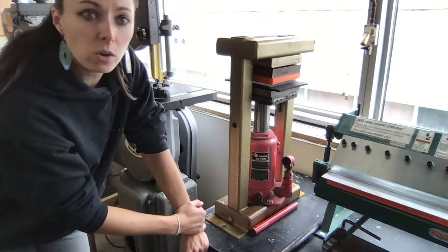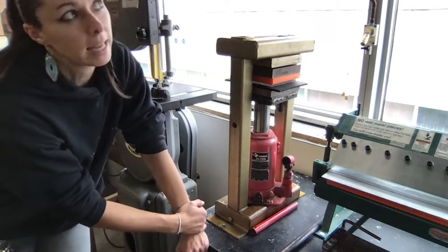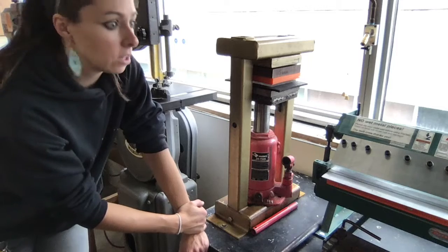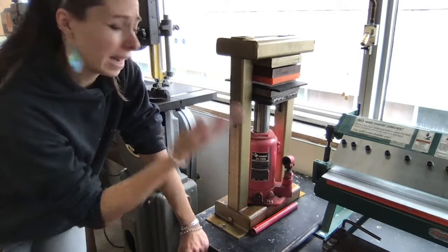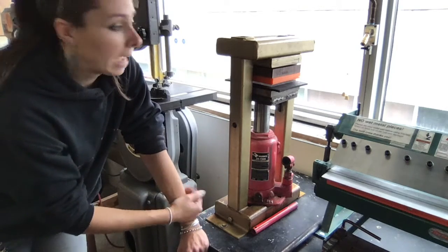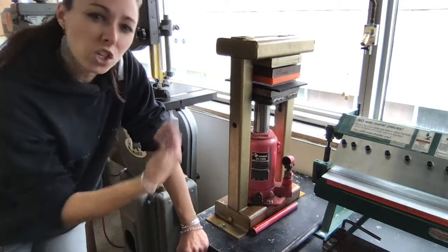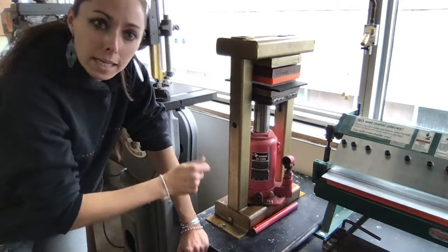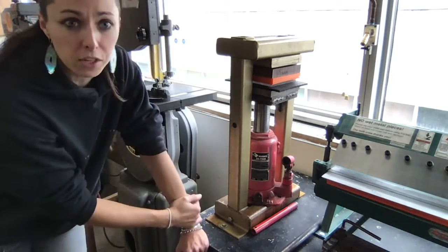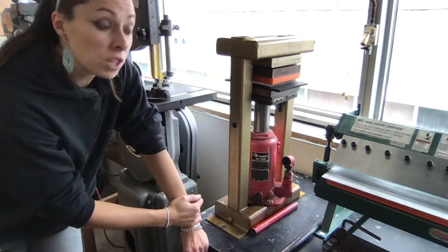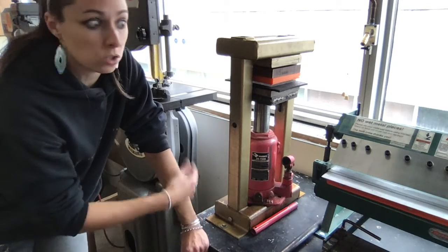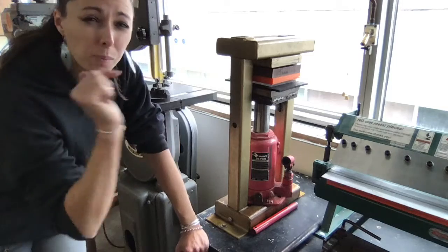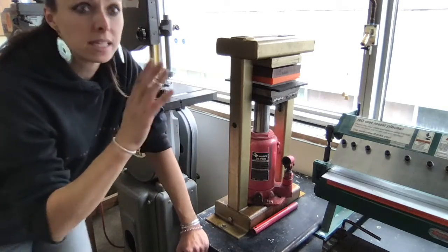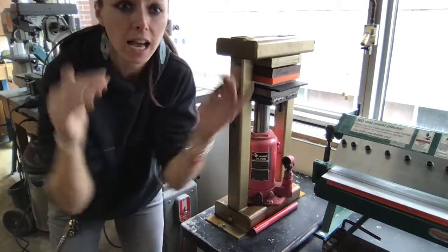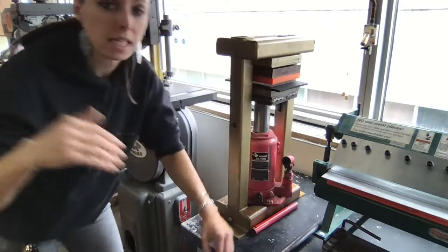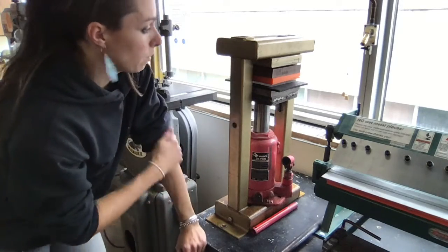As you're working it out, depending on the thickness of your metal, depending on how well you annealed it, there's a lot of different variables, depending on how deep you want it. You might have to die form it a couple of times or check in on it as you're pumping to make sure it's the depth that you want. If it's too thin of metal, you do risk sort of cracking it or ripping it at the flange. So basically where the metal forms into the die and where that flange stays on the top of the die.